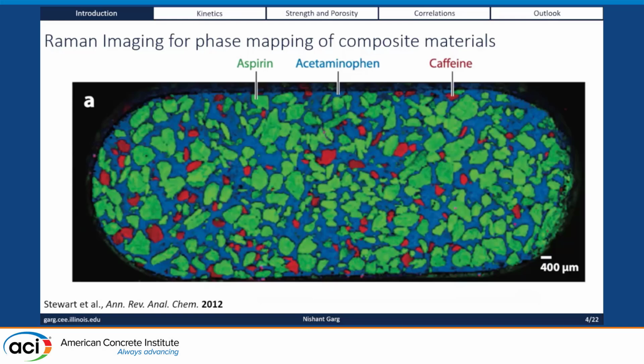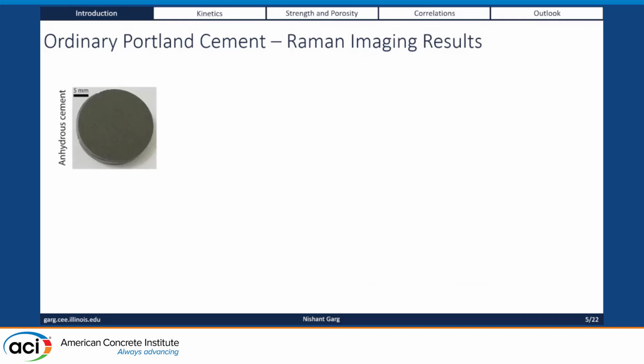Which you need when you're sick. So what we thought, well, why don't we do the same thing on cement, right? And people have been doing that with SEM-EDS for a long time. We want to do this with Raman imaging and see what we can get. So we make this kind of a little pill, which is essentially cement embedded in epoxy.